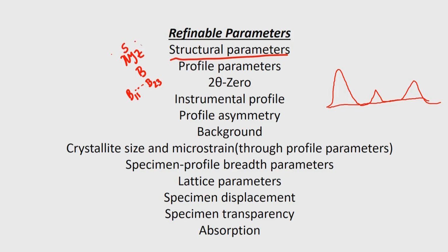So, these now define our structural parameters. Now here what we are doing is to put the bismuth and the oxygen positions into this one and do a refinement, and then do the difference Fourier map. And every time we do the structural parameters, we should also refine the profile parameters. The way it is done is in fact very well organized, and that is known as the Rietveld refinement,